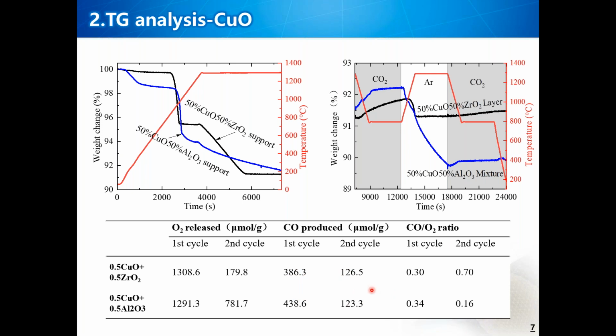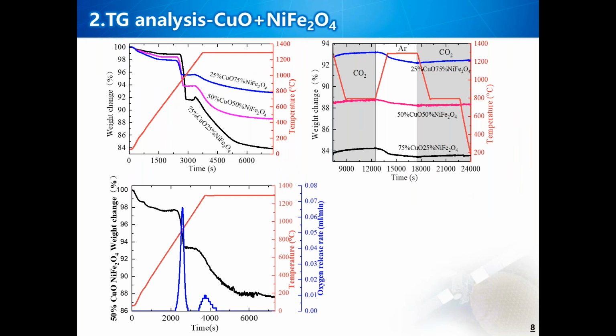Therefore, it is envisaged to combine the two to get a suitable preparation so that the catalytic material has high stability and high CO yield at the same time. So copper oxide has a good performance of releasing oxygen and absorbing oxygen. So we consider to use CuO and nickel ferrite for testing at the same time.